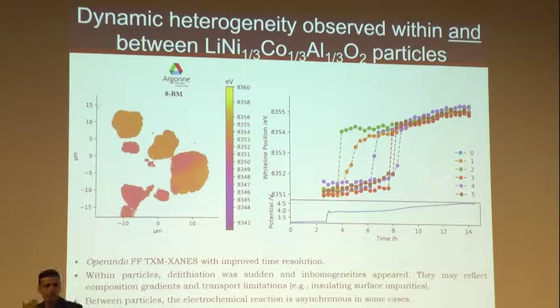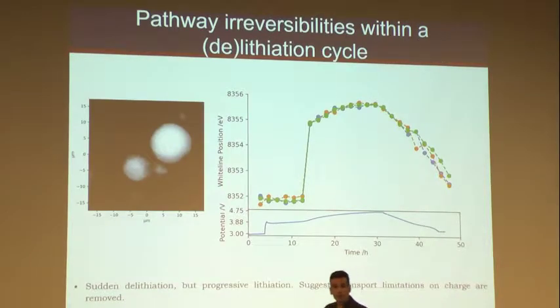And we think that there's a blocking effect, that you need enough energy for the particle to have a driving force to dilithiate. And once it goes over that insulating layer, it has so much driving force that it goes very quickly. That's the way that we're interpreting this. That insulating layer could be lithium carbonate. If that's the case, by the time you've charged it, it's burned. Lithium carbonate is not stable at these potentials. And so that could explain why when you go on discharge, when you reduce again, the particles transform progressively, which is what we would expect based on the mechanism at the bulk average for these materials.